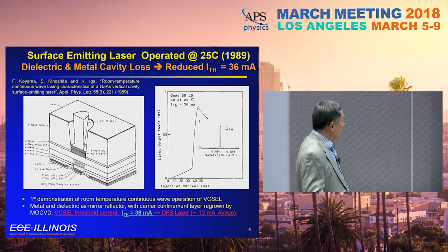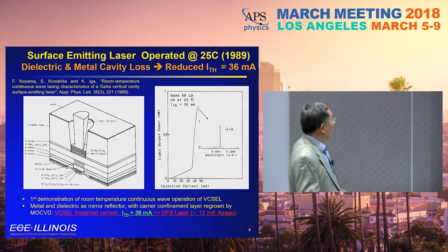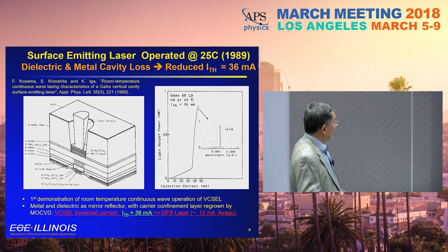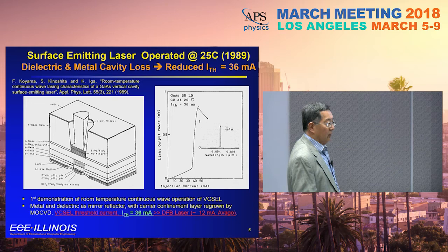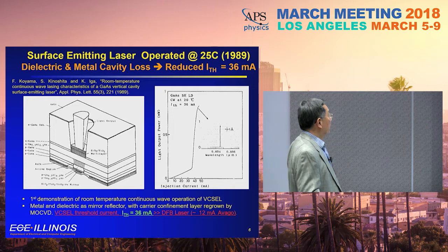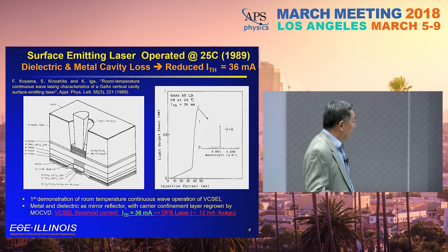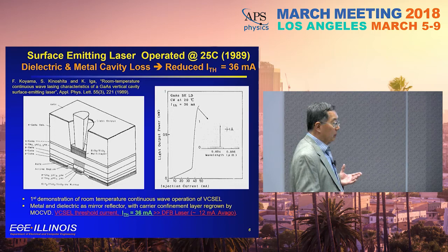Subsequently, development using a DBR—a dielectric DBR of SiO2 and TiO2 on the bottom, with a DBR plus gold metal on top—brought the threshold down. The threshold at that time was still high at 36 milliamps, but changing from 900 milliamps to 36 milliamps was a fantastic development that took 10 years. It takes a lot of people's ideas integrated together. This resulted in the first room-temperature operation at 25°C, but the 36-milliamp threshold was much higher than today's DFB lasers, so application was still limited.